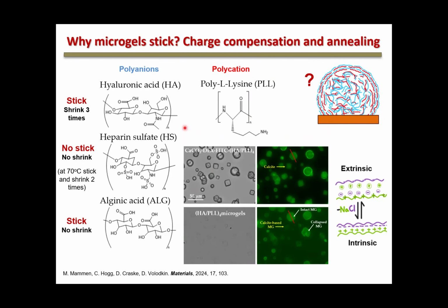So to understand the mechanism of adherence or adhesion, we prepared microgels using one polycation, polylysine, and 3 different polyanions: hyaluronic acid, heparin sulfate, and alginic acid, or alginate. You can see they're all polysaccharides, but they have different charge density. If you go down, this is the highest, this is the lowest, so the charge density of them is varied. And we found that, for instance, those microgels made from polylysine and hyaluronic acid stick to the surface, and at the same time they shrink 3 times during formation, but they stick very strongly.